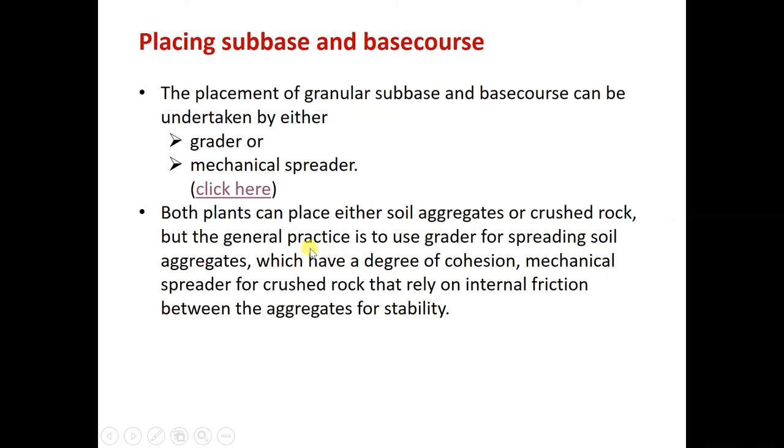But usually, here it says the general practice is to use a grader for spreading soil, whereas for the aggregates, which are the crushed rocks, it's better to spread by the mechanical spreader. But I think we see a lot of the time the contractors just use the grader to spread the aggregates. From the point of view of which is more efficient and better, the best practice is that the aggregates should be spread by the mechanical spreader, whereas for the soil, for subgrade, where we shape the crossfall of the subgrades, that one is better done by the grader.